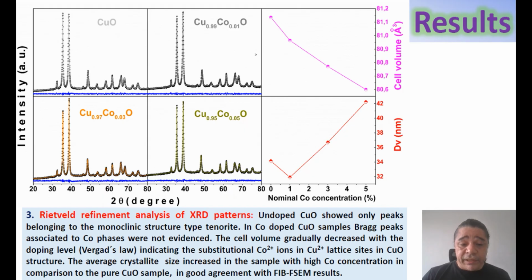The average crystallite size increased in the sample with high cobalt concentration in comparison to the pure copper oxide sample. The results are in agreement with field emission scanning electron microscopy.